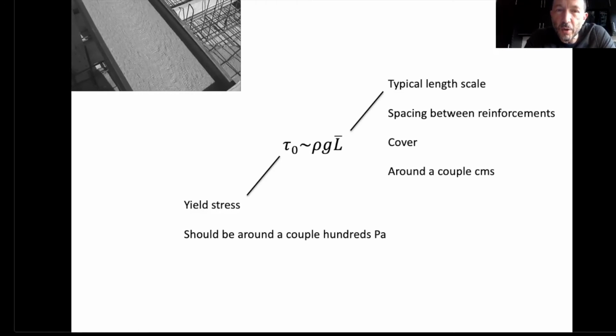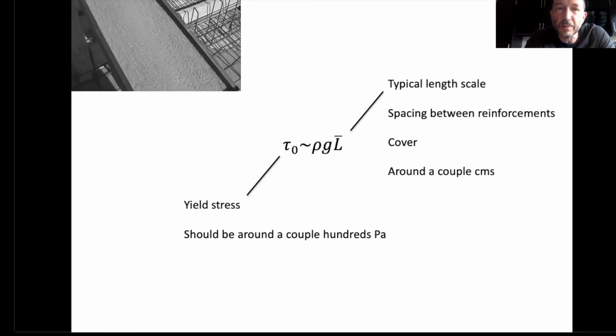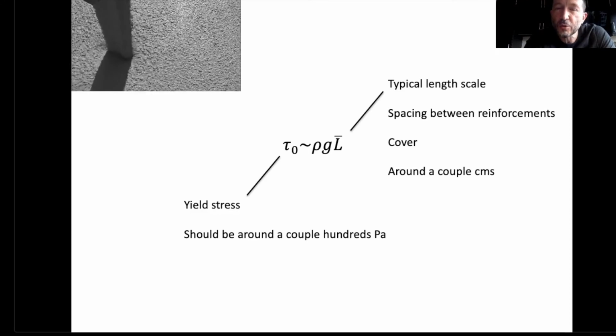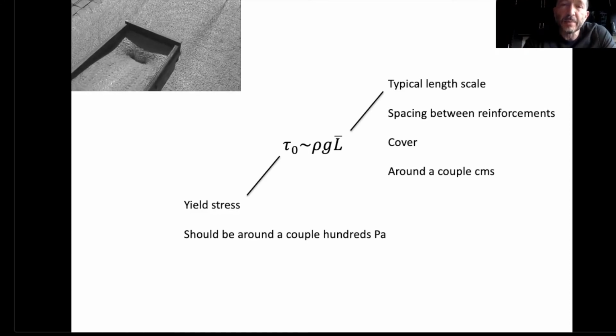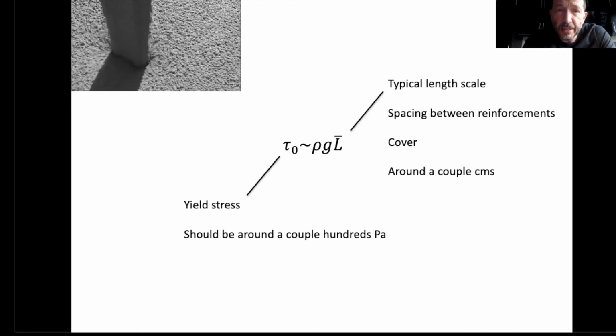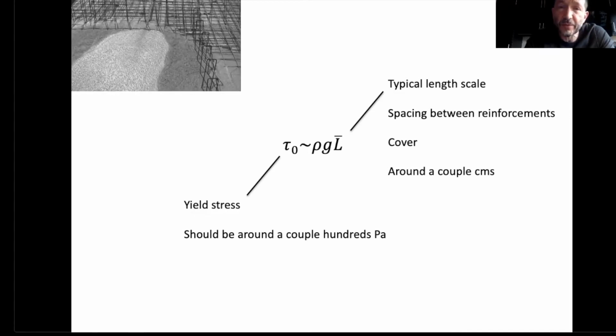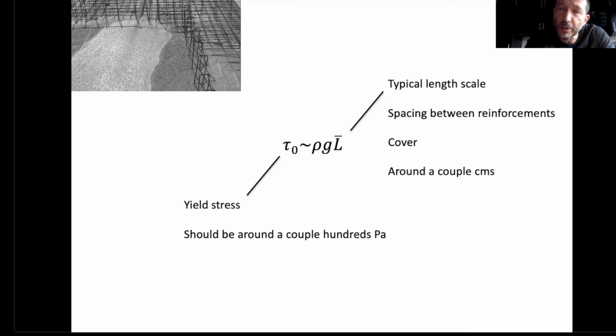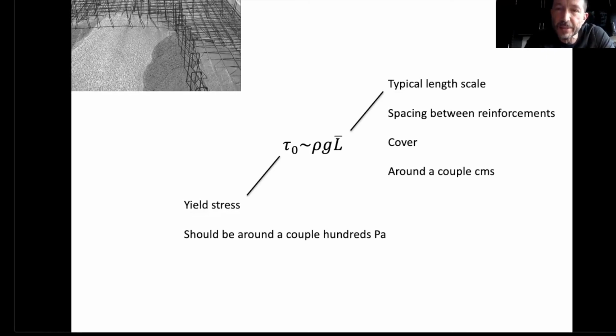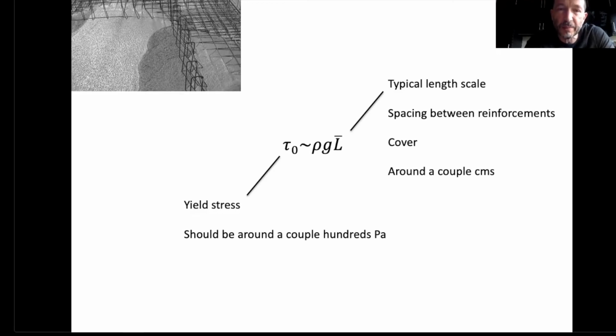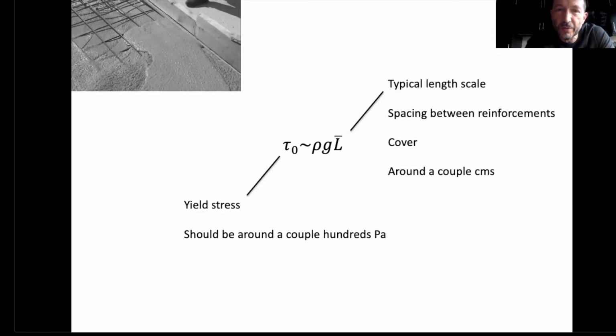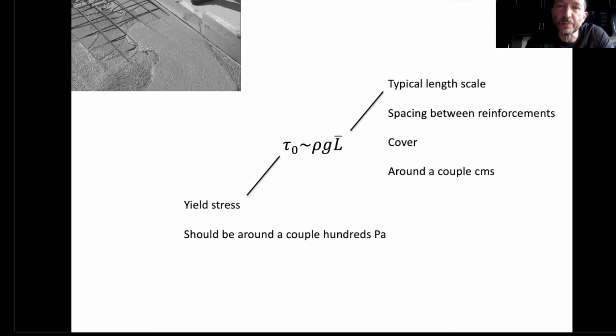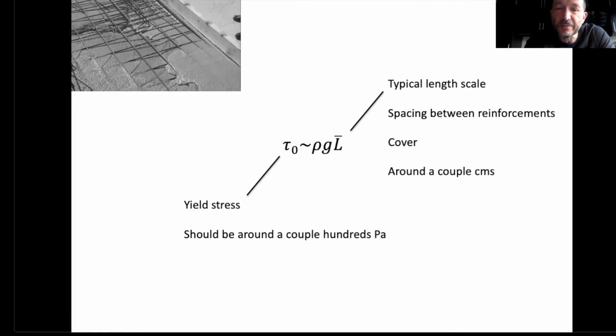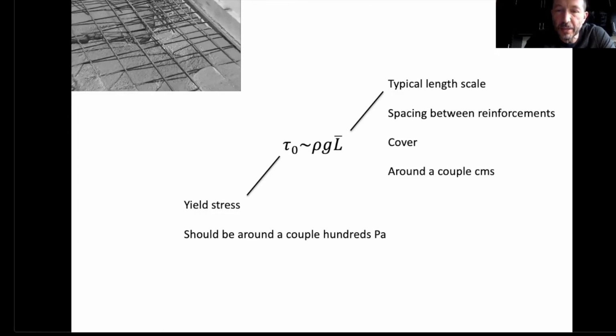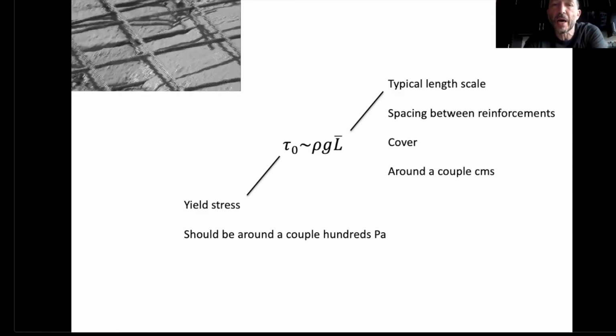A yield stress that is so low that the material is able to fill most formworks, even the most complicated one, to go through very dense steel bars. But keep in mind that we can't design materials that have no yield stress at all. That would be perfect to fill anything, but with no yield stress, we're going to face the difficulty we have already discussed, stability. We need a yield stress at the level of the cement paste for the cement paste to be stable. Moreover, this cement paste needs to carry the aggregate in the suspension. So we will always need a minimum value for this yield stress. But if this yield stress stays lower than, let's say, 100 Pascal, we are able to fill most molds, most formwork in most conditions.